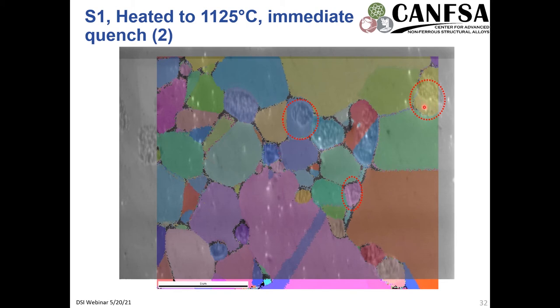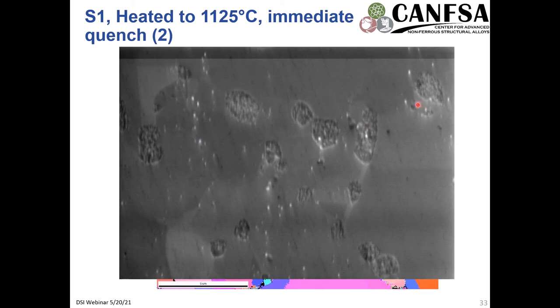And I should note that the EBSD technique really is not able to distinguish between the gamma and gamma prime. So right now we're going based upon morphology and topography of the material in the mechanically etched microstructure that we're seeing here. And so we have this region right here and right here as well.